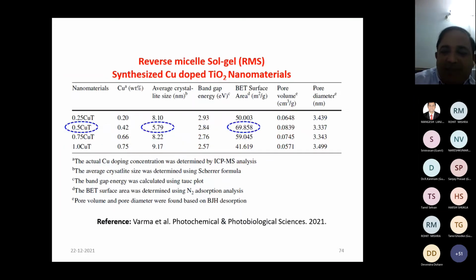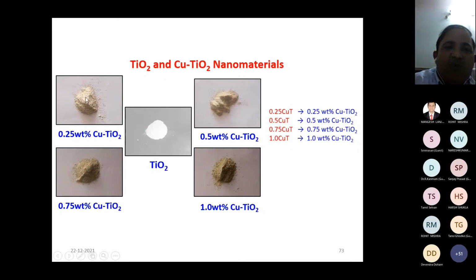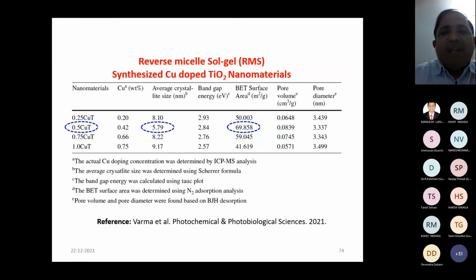So we synthesized both classes of material. Here we have pure TiO2, and here we have 0.25% copper doped TiO2, 0.5, 0.75 and 1% copper doped TiO2. Now we try to check its activity, and before that I will summarize its properties. If you remember, in the Sol-gel method we were getting a crystallite size around 23 to 25 nanometer. Here we are getting crystallite size in single digits for all the cases. So we have better control on size, and that's why its surface area also increases, nearly 70 square meters per gram in the case of 0.5 copper doped TiO2, and all the properties are better in 0.5 copper doped TiO2. We use this material to carry out our degradation work for levofloxacin.